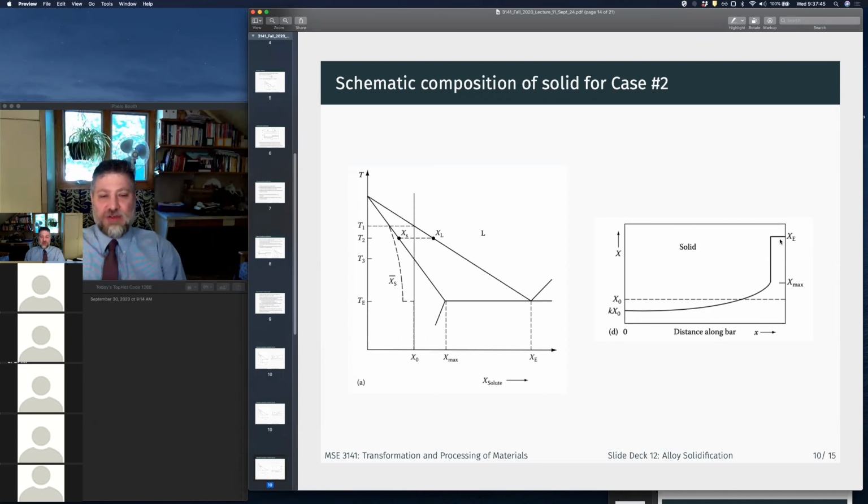Because what this tells you is that for a weld pool, if you do a spot, and you're using a filler metal, you're going to have a composition gradient, not just in the spot that was melted and mixed, but within the melt pool, right? So after you solidify, the composition of your melt region is not going to be homogeneous.